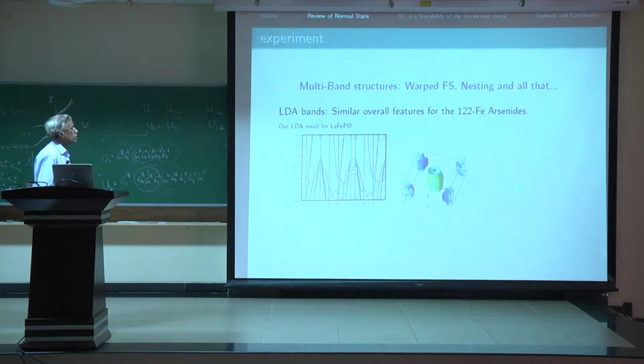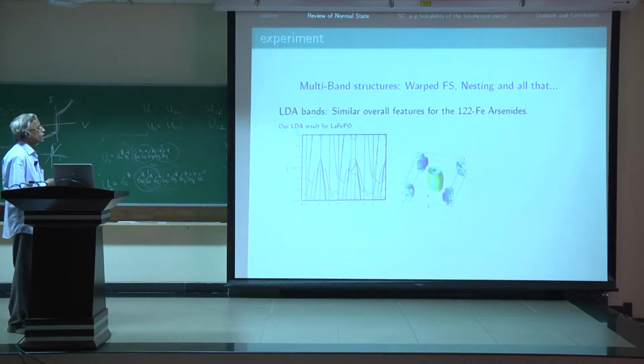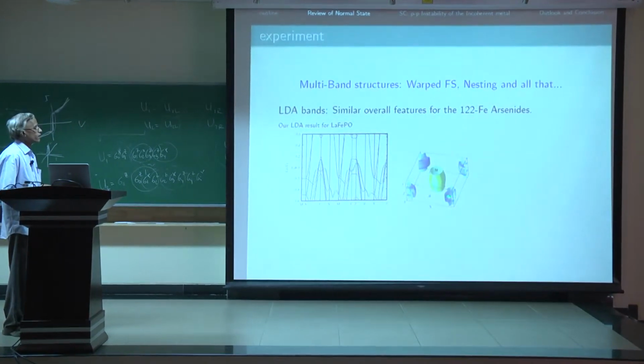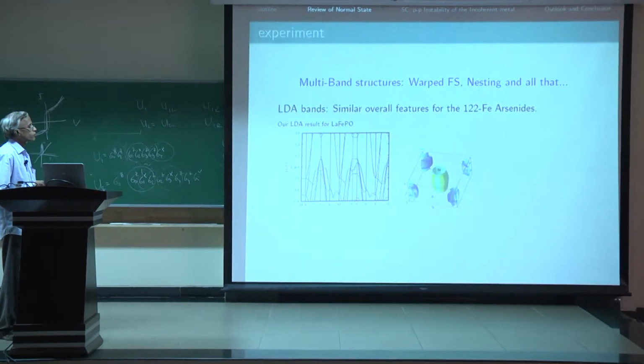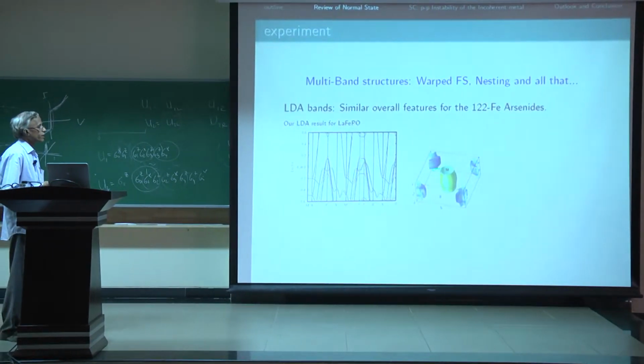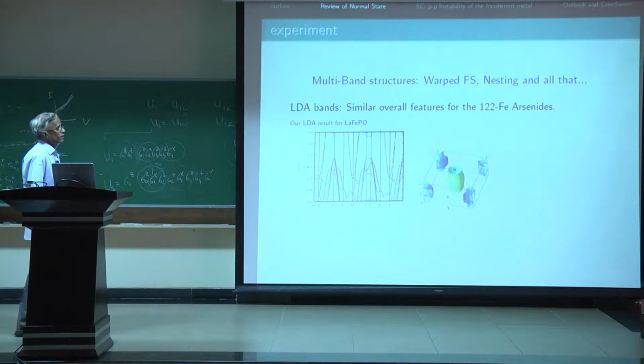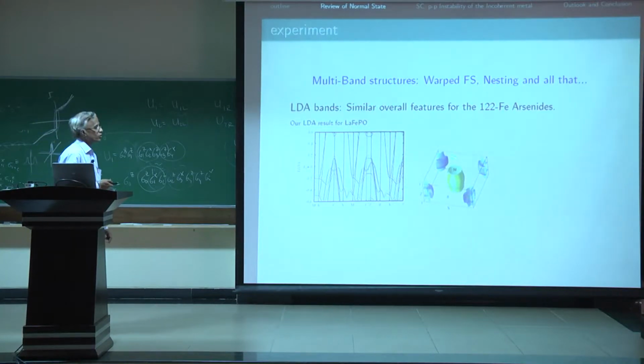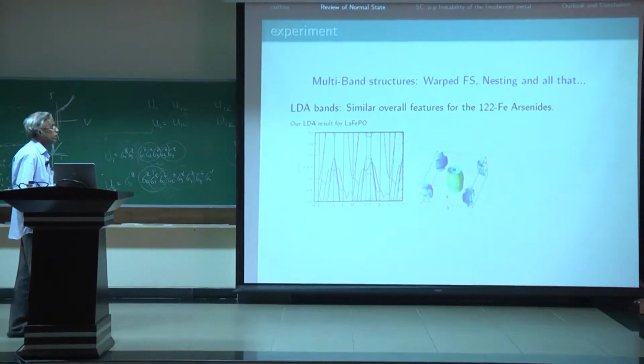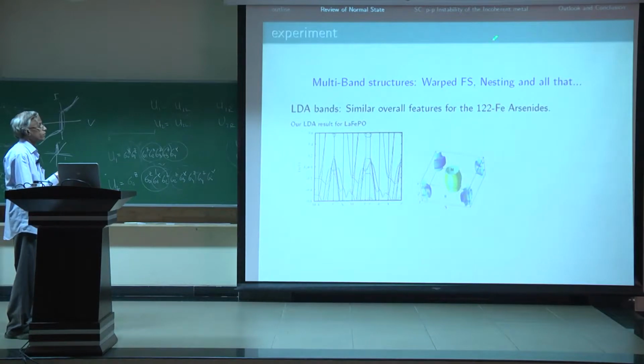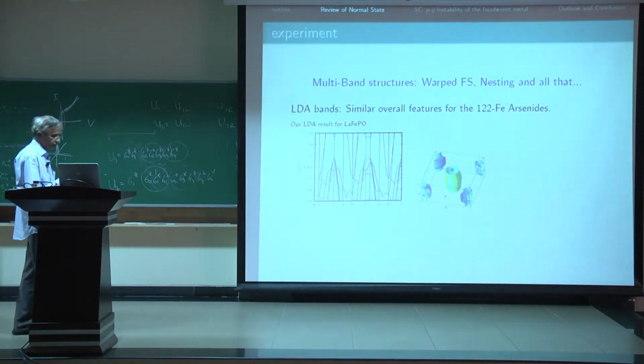Okay. So this is another example for LaFePO, wherein you see that the Fermi surface corrugation out of plane is appreciable, and in fact, this may have something to do with the fact that one observes nodal superconductivity in this system, as in many of the 122 iron arsenides, which I'll come to.